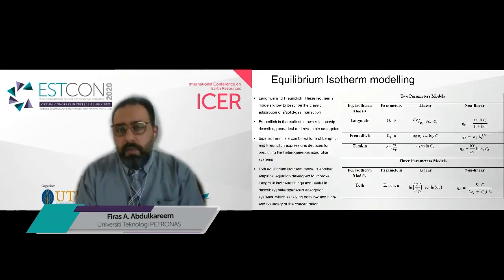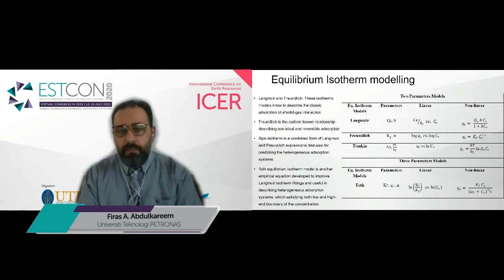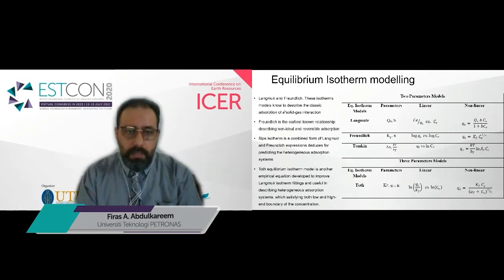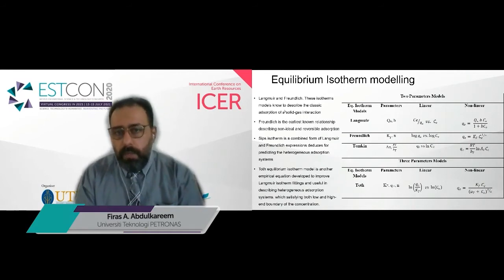The equilibrium isotherm models applied here are split into two-parameter models and three-parameter models. In terms of the two-parameter models, we utilize the Langmuir, Freundlich, and Temkin models. The Toth model, which represents the three-parameter models, is usually utilized to analyze the adsorption measurements, whether homogeneous or heterogeneous, while Langmuir, in terms of two-parameter models, is usually applied on the adsorption data to analyze whether the adsorption is monolayer, compared to the Freundlich, which always supports multilayer and physical adsorption, while Temkin is usually related to the adsorption with the impact of temperature on the gas molecules' interaction with the surface of the solid adsorbent or the porous material.